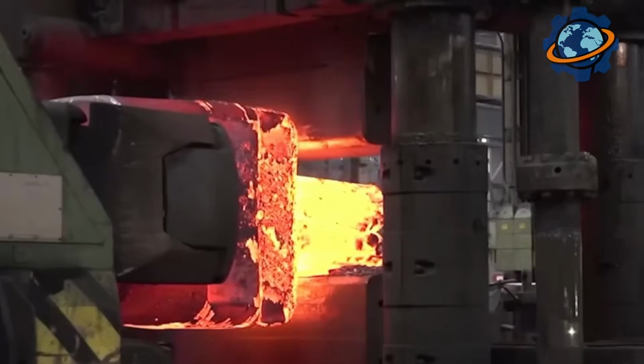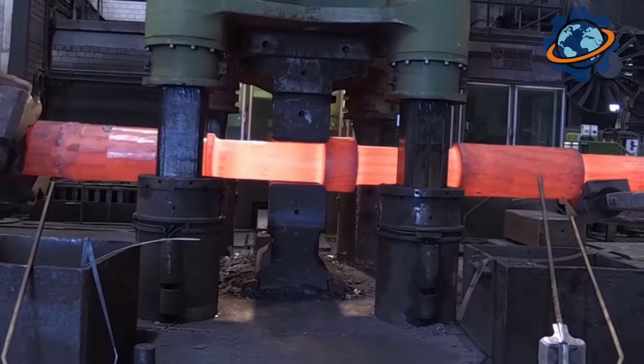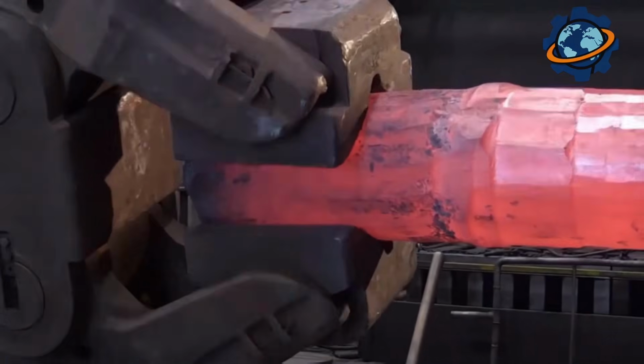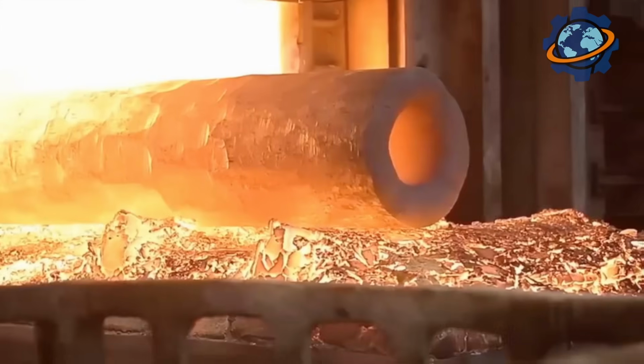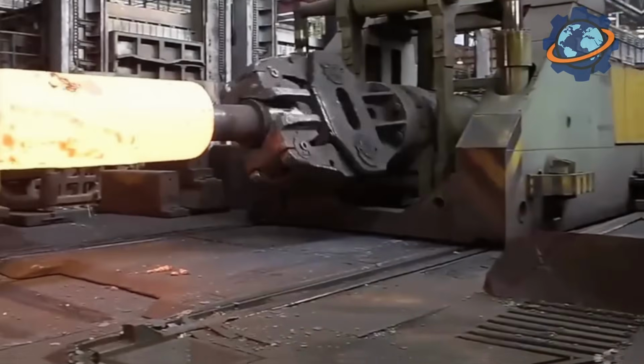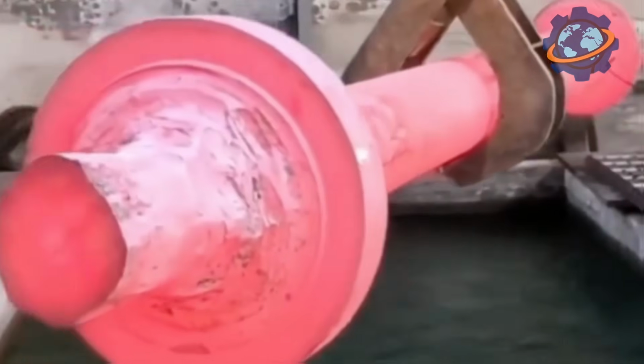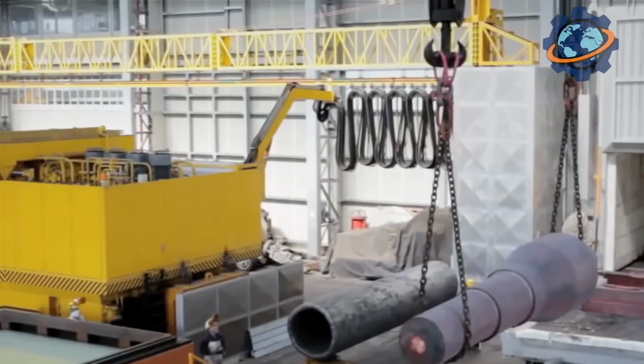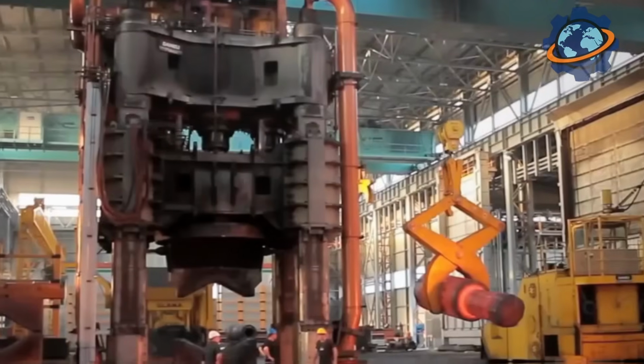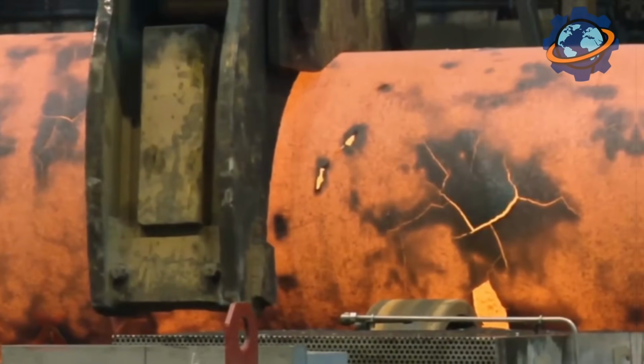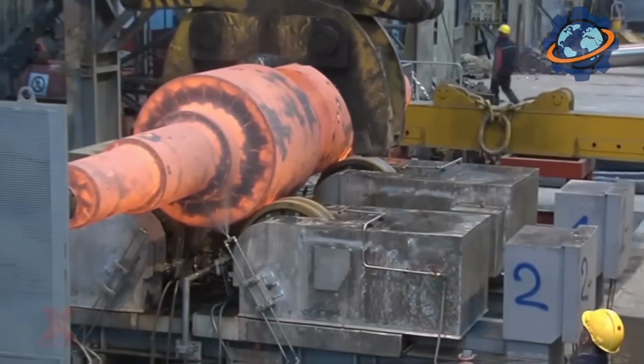After the second forging stage, the shaft undergoes heat treatment, normalization, and tempering. It's heated to 1600 degrees, then freely cooled at a rate of 50 degrees Fahrenheit per hour. The entire cycle takes about 5 days. This slow heat treatment relieves all residual stresses and ensures stable mechanical properties along the entire length of the shaft.